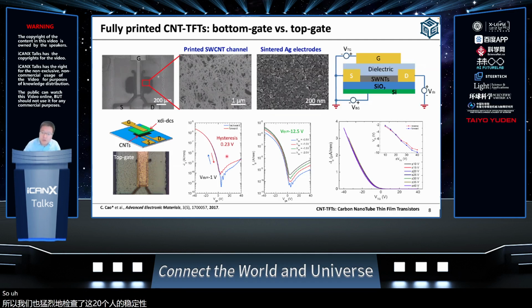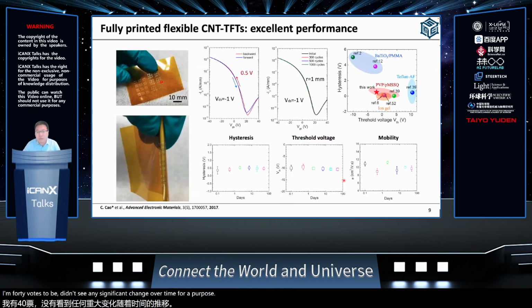Using the stress analysis, when we increased the bias voltage from 0 to 40 volts, we didn't see any significant change of the transfer curves. So our fully printed flexible CNT TFTs have excellent performance in both bending and reliability tests. The device can still work very well, even after bending over 1,000 times at a small radius of 1 millimeter.